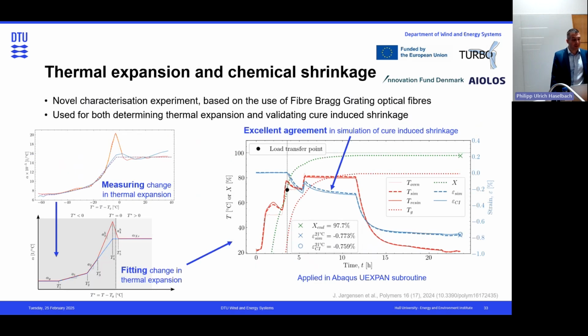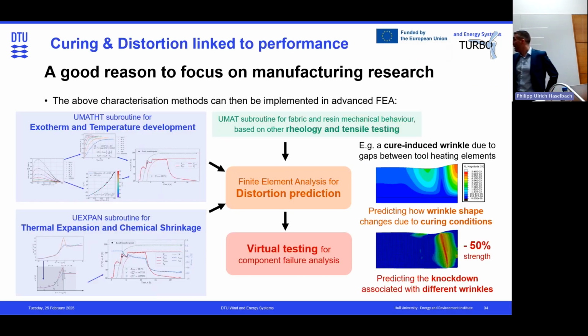With that, we get a quite good idea of the impact of the cure kinetics on the residual stresses, and implement this into a finite element software again. So meaning we do again a coupling with our simulated blade, and couple the residual stresses to the blade model, and then we can see, for example, that wrinkles can occur due to the residual stresses. And I think that is really a breakthrough.